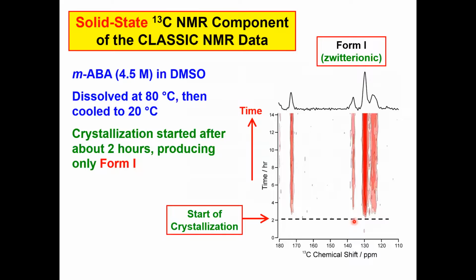You know, nucleation is a rare, stochastic event, and in this case, the solution had to wait for around 2 hours before the right critical nucleation cluster arose before crystallization would then proceed. So this is quite important in our subsequent discussion: induction time before crystallization begins. In this particular case, we get form 1.